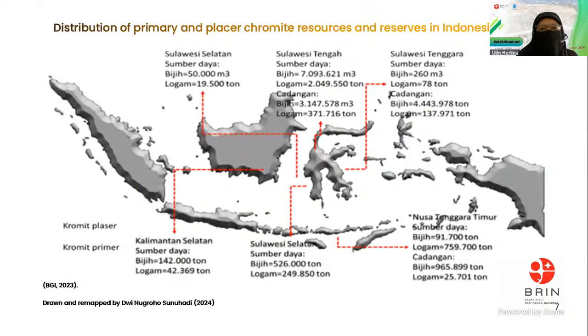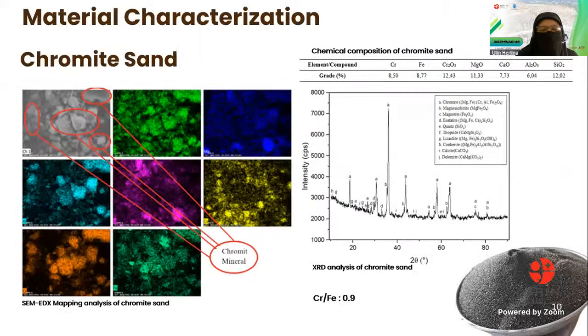This is the distribution of primary and placer chromite resources and reserves in Indonesia. Most of the potential chromite is located in Sulawesi, Kalimantan, and then Nusa Tenggara Timur. And then this is the material I use in this research, chromite sand. It's from Morowali, Central Sulawesi. The grade of chromite sand is very low because the chromium content is 8.5%, and the ratio of chromium to iron is only 0.9.